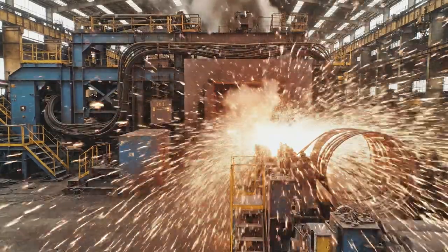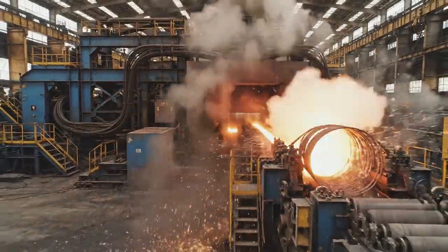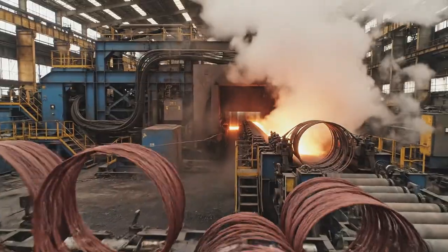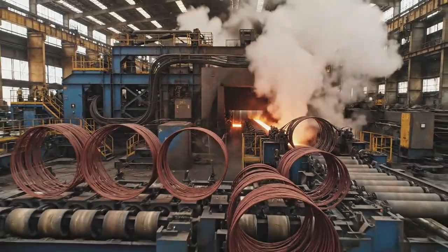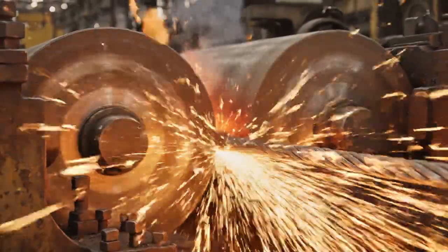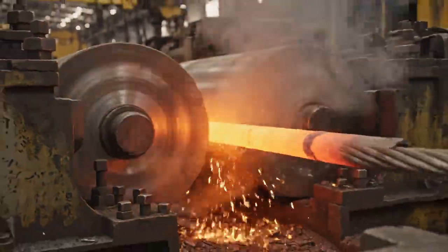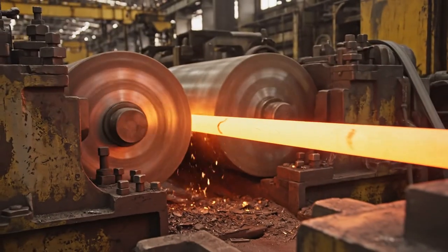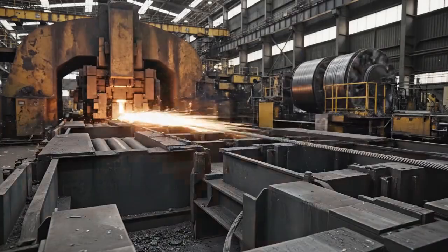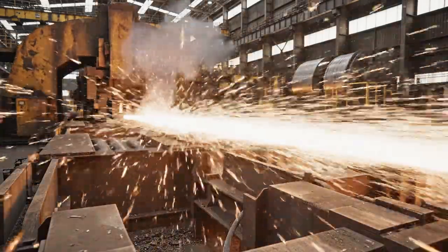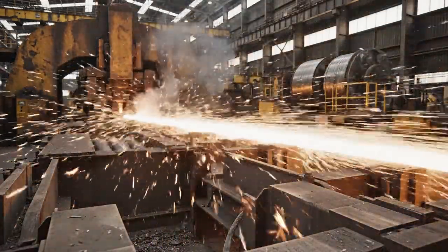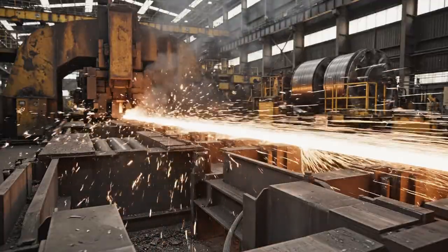This is the heart of the process, the finishing block, where the raw material is transformed into high-quality wire rod at incredible speeds. Here, the carbide rolls spin at phenomenal speed, reducing the diameter of the glowing wire rod to its final size. The wire rod, still glowing hot from the furnace, exits the finishing mill at speeds exceeding 100 meters per second.